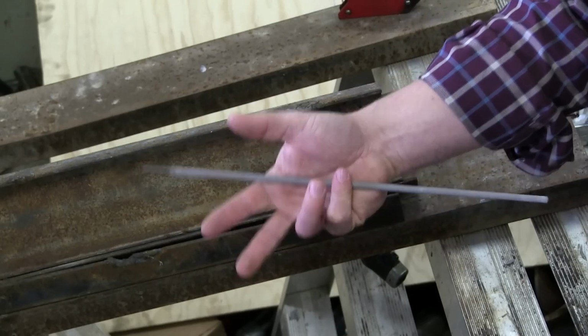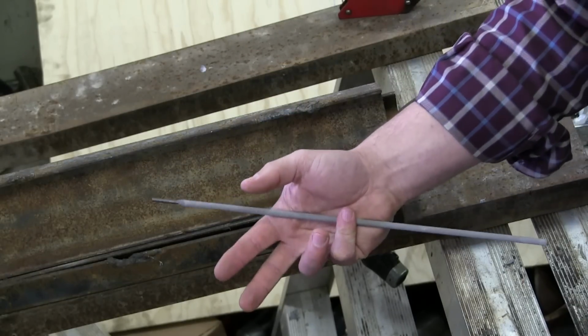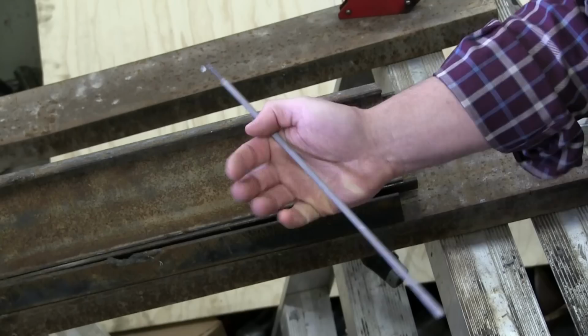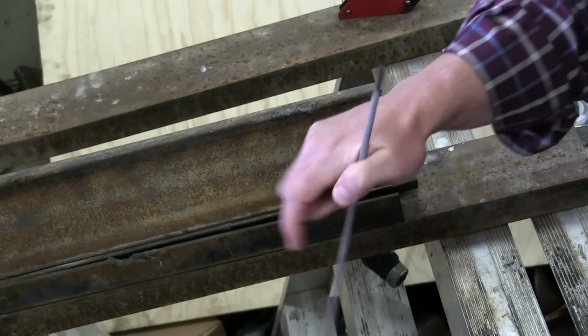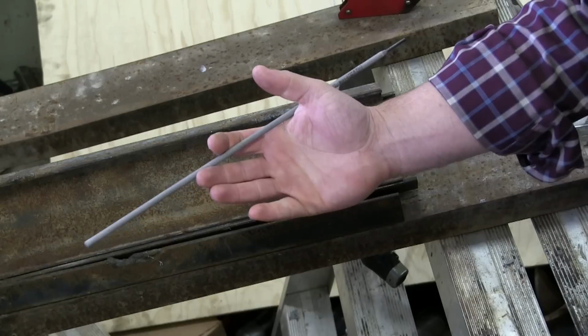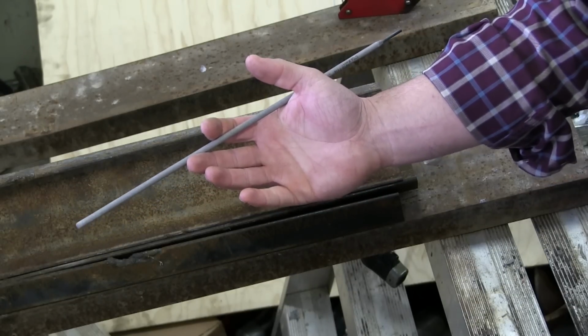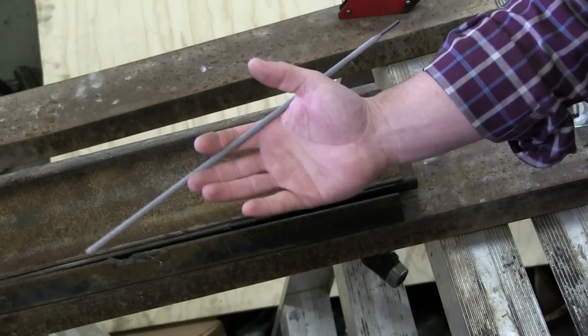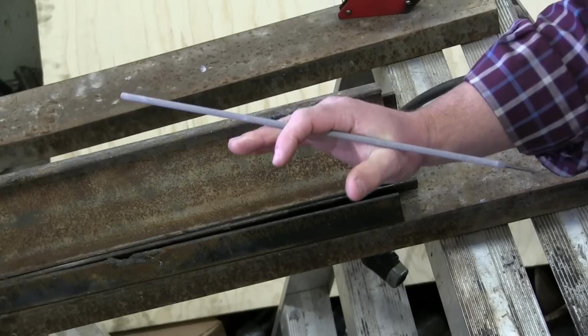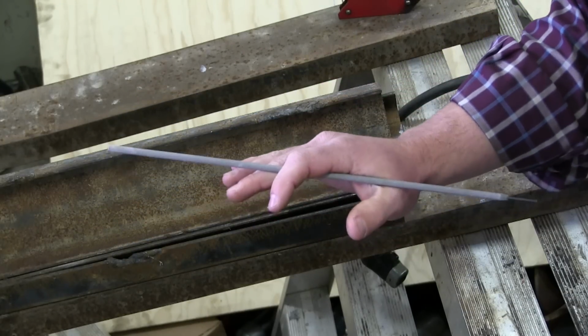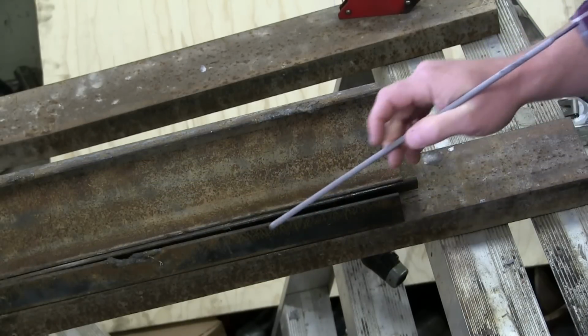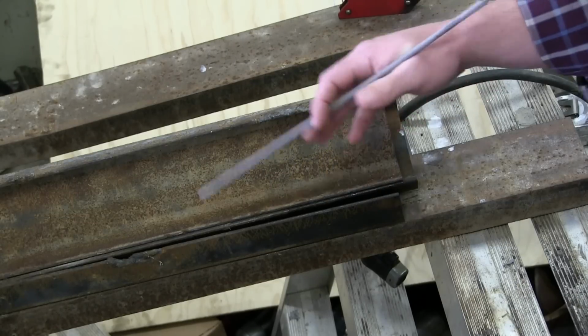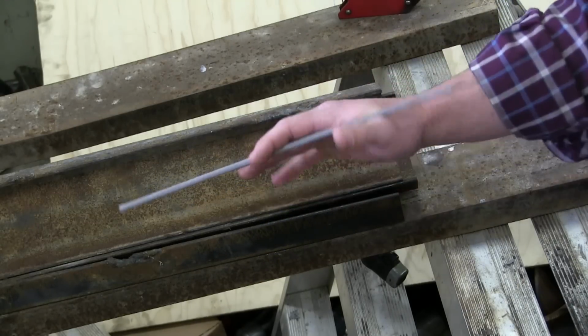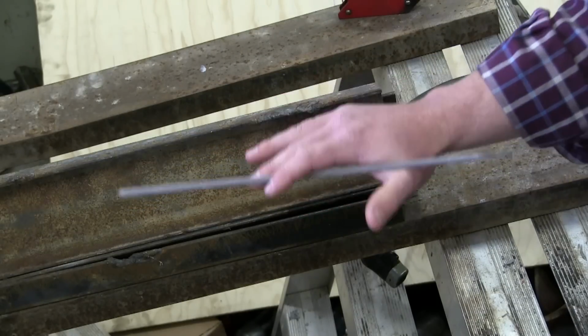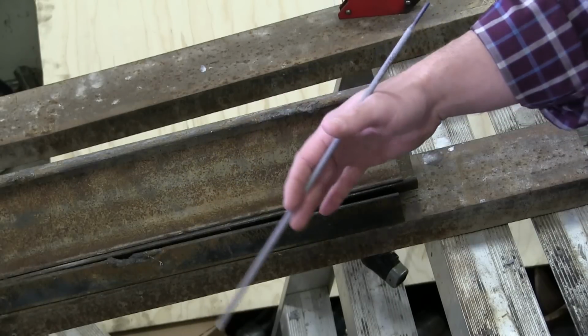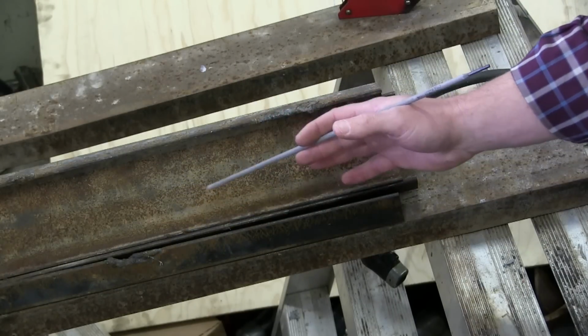And 60-10. Now 60-10 is very special. It freezes fast, so it kind of is ugly. This freezes a little slower, so it smooths out your ugly edges. There's also what they call jet rod, which is 70-14 or 70-16, something like that. And jet rod freezes really slowly, so it looks beautiful, but it is very susceptible to having scabbiness on, you got to prep better. So this 70-18 is a very nice rod to learn with because it's a good balance of, you don't really need to prep that well.